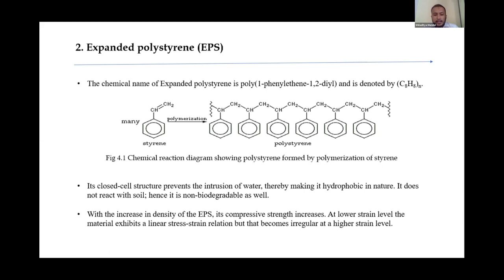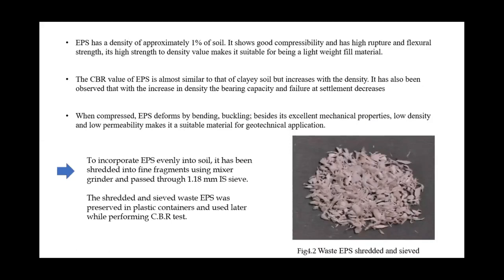So with the increase in density of the EPS, its compressive strength increases, and that's what we have tried to utilize the utmost out of this material. EPS has a density of approximately 1% of soil. So that shows how light this material is, it's very less dense compared to any other granular material such as soil. So this EPS shows good compressibility, and it has high rupture and flexural strength, and its high strength to density ratio makes it a very suitable material for being a lightweight fill material.